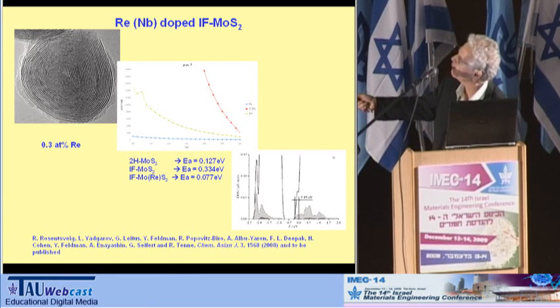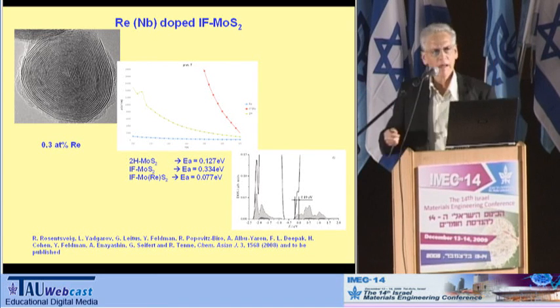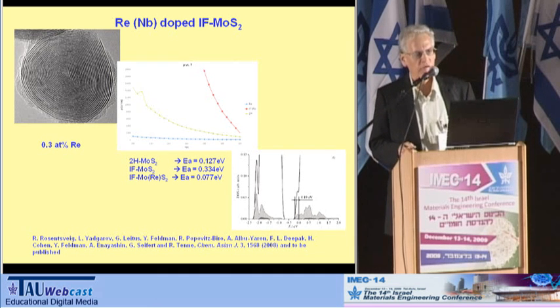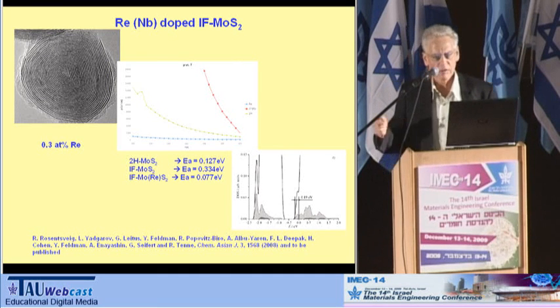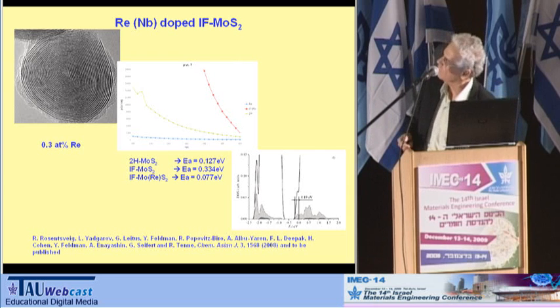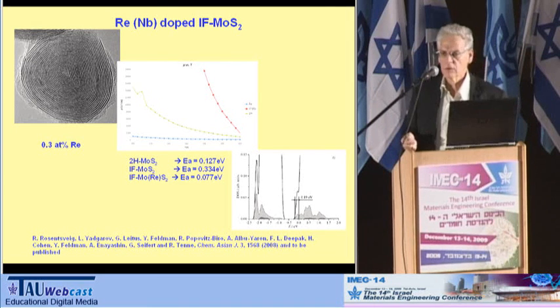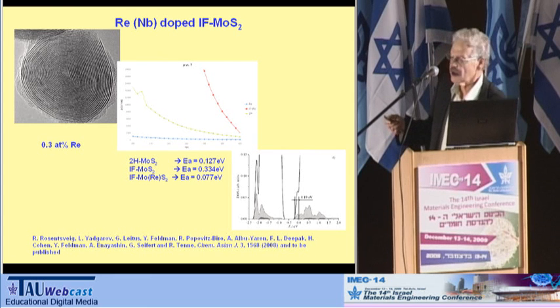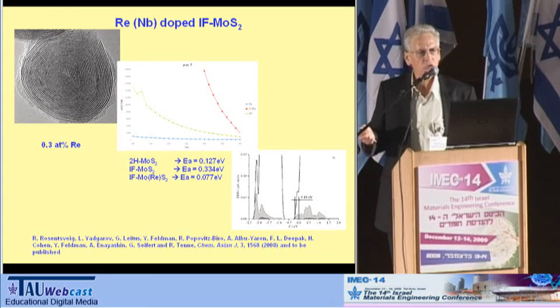So this is the resistance versus temperature. This is the pristine material, and when we dope it, it becomes like that. I won't be able to elaborate very much on the doping process. Some of it has been published, but the more recent work is not published, and we are not able to describe in detail the reaction, the growth process. Nevertheless, it comes very close to the calculation.